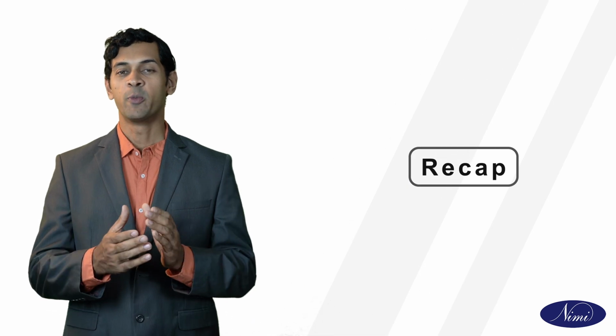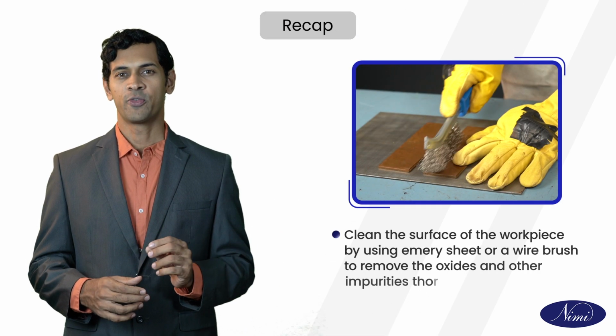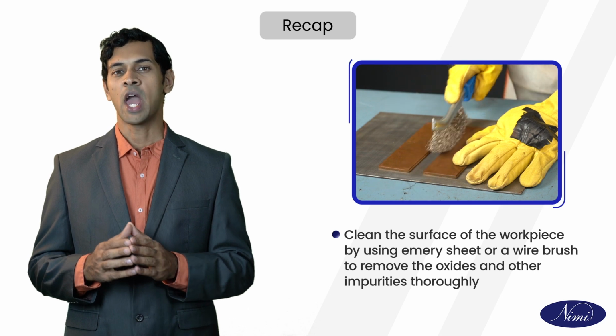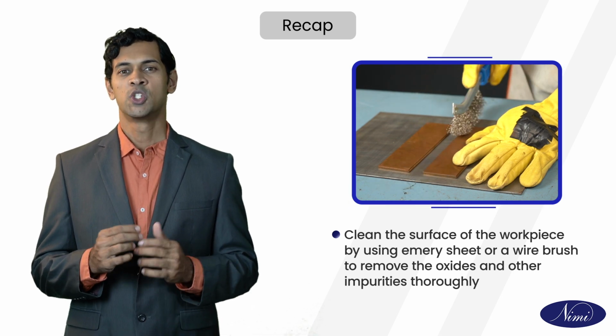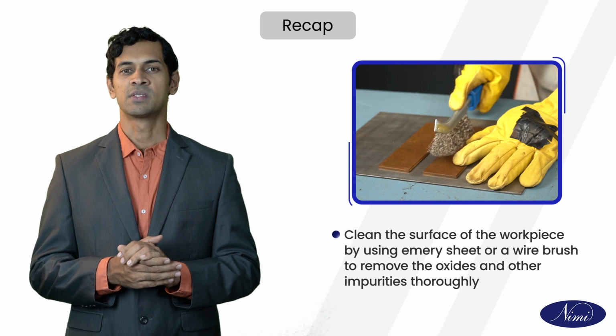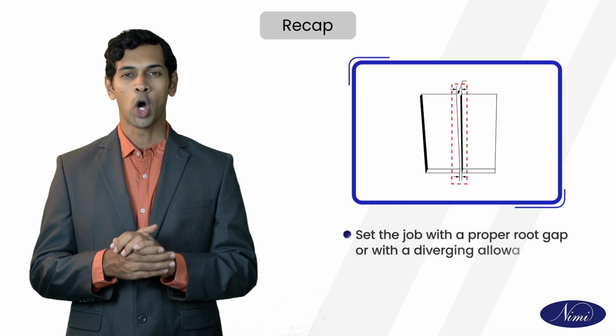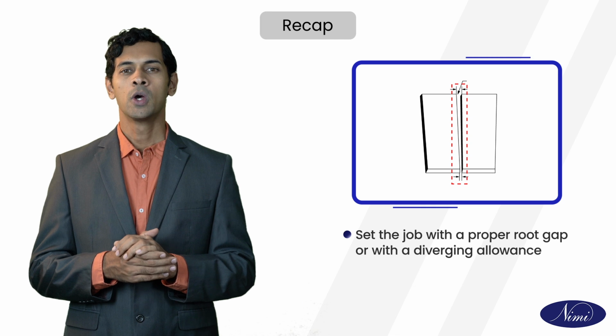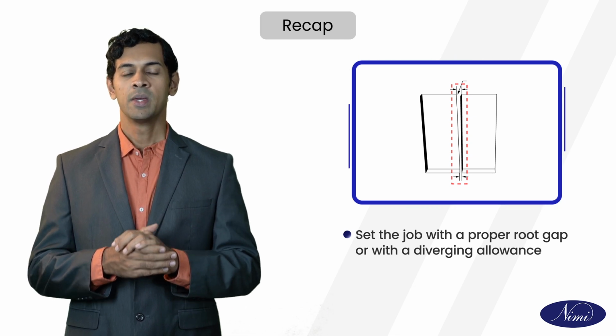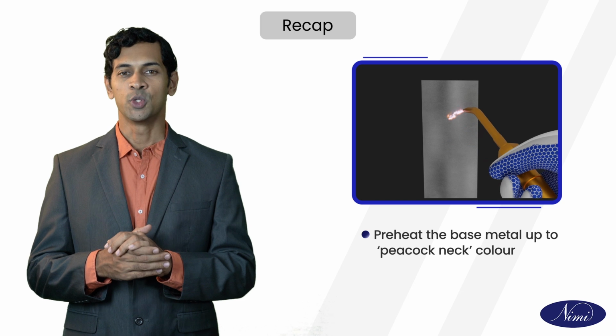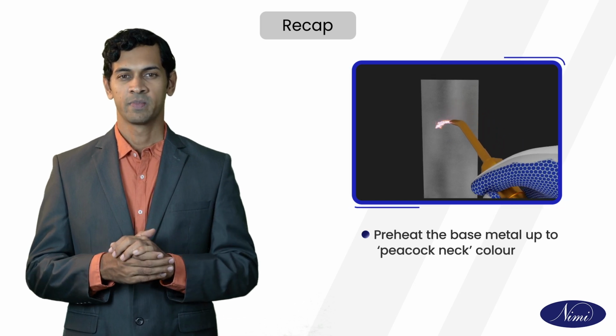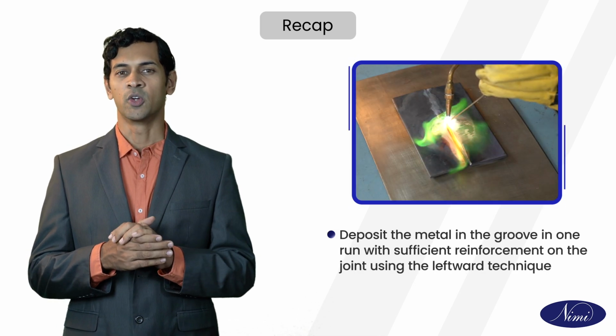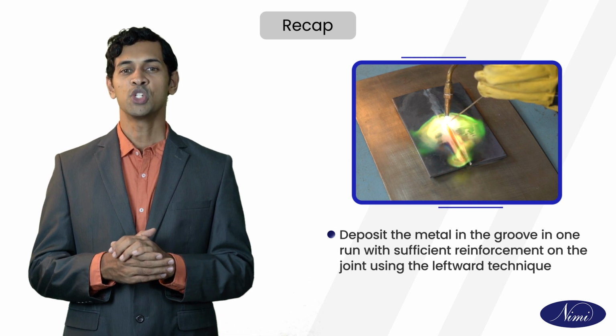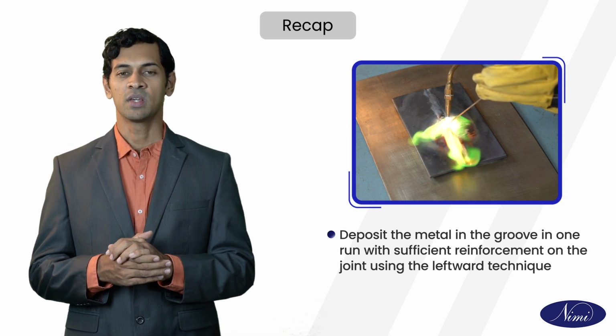Let's recap the key points discussed. Clean the surface of the workpiece by using emery sheet or a wire brush to remove the oxides and other impurities thoroughly. Set the job with a proper root gap or with a diverging allowance. Preheat the base metal up to peacock neck color. Deposit the metal in the groove in one run with sufficient reinforcement on the joint using the leftward technique. This brings us to the end of the session.